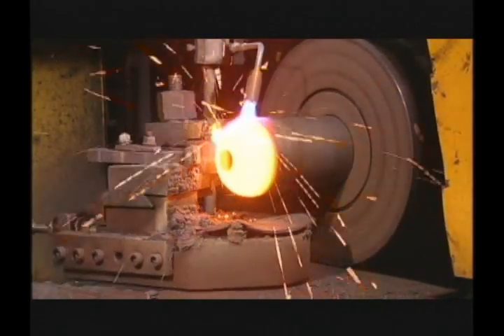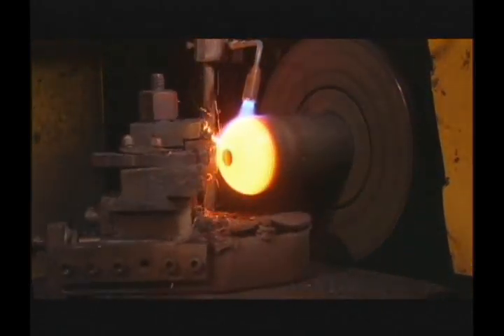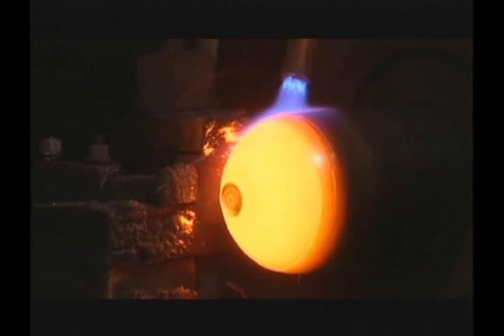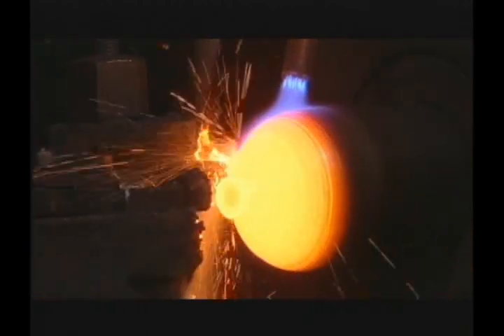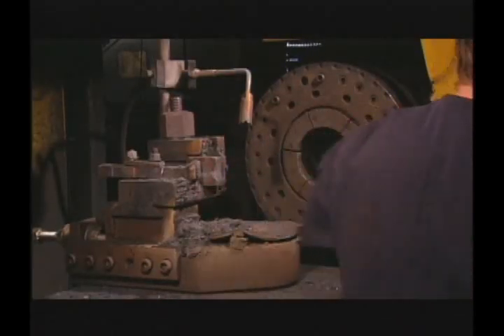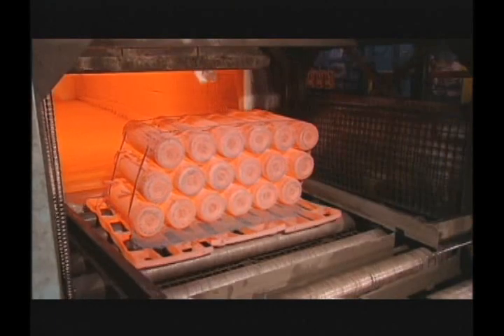Using synchronous movements of two axes, the machine gradually forms the shoulder and neck areas of the cylinder. The hot spinning process must be carried out with care and expertise so that folds or other defects are not introduced into the neck area of the cylinder. Shoulder profiles are normally hemispherical in shape, with the thickness approaching two to three times the sidewall thickness near the neck. Worthington cylinders are closed completely prior to heat treatment, which minimizes interior oxidation for a smoother surface finish.